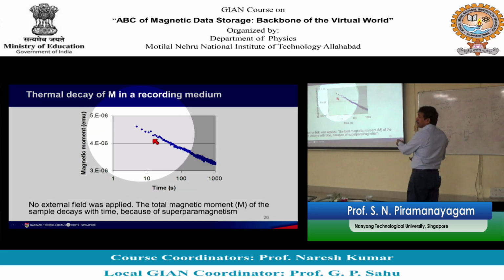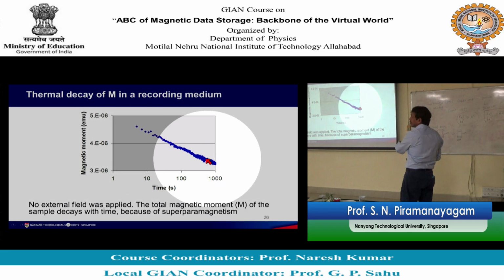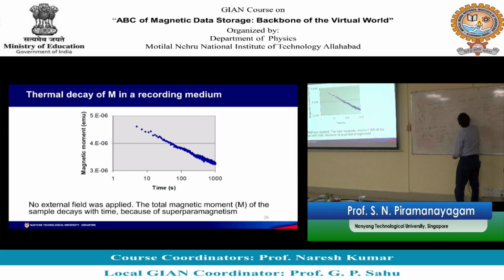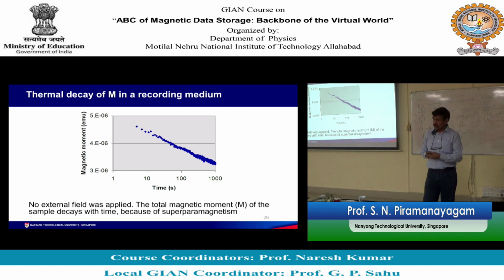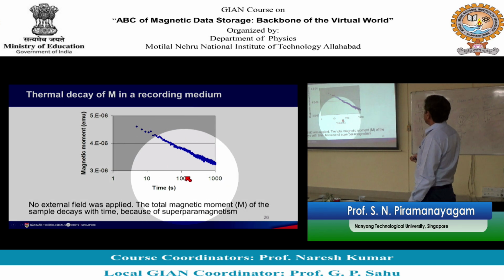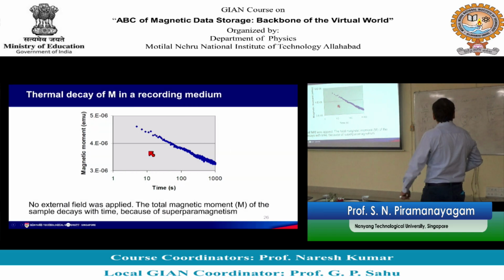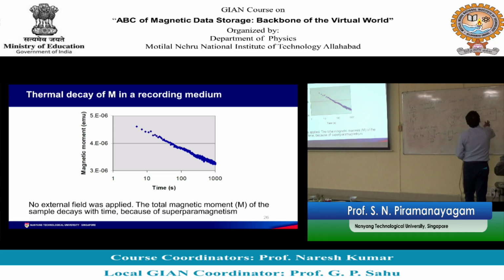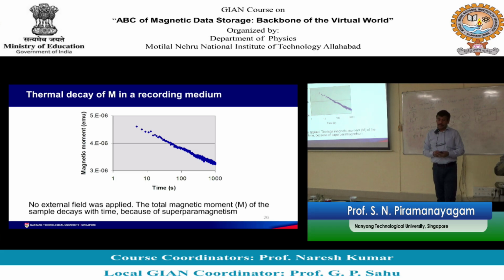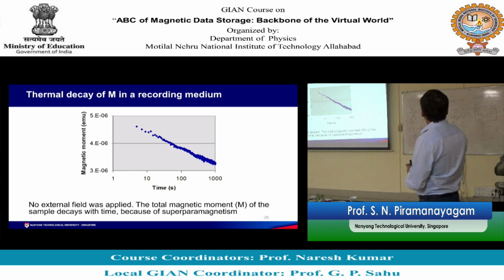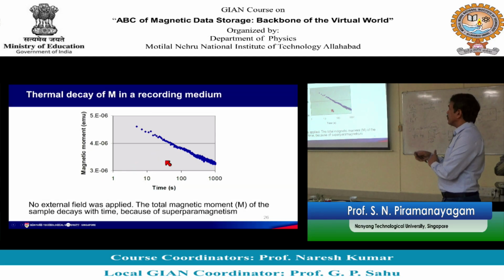When KUV by KBT is 45, then this drops. This is not good, this is not desirable. Here you see within 1000 seconds the magnetization drops so much. When this number is larger than 60, then the data will be stored for many years. For example, the samples of 2000 or before have a very large volume, so KUV by KBT is much larger than 60. But somewhere in 2000 we started having this problem. We entered a region where the KUV by KBT becomes comparable to 60.